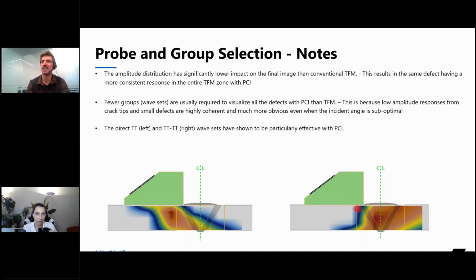Maybe in the top corner here, a little bit better, not quite as good, but that's to be expected. But in general, when using PCI, the TT and TT-TT groups are going to be extremely effective, and we can usually cut out some of our groups. So say for this weld inspection, if we wanted to cover the entire part for all the different types of defects possible, I might actually need 4 groups, 2T, 3T, 4T, and 5T to get a good distribution. But actually using PCI, which is these two groups, we're going to have a better image than we would with 4 groups using conventional TFM.